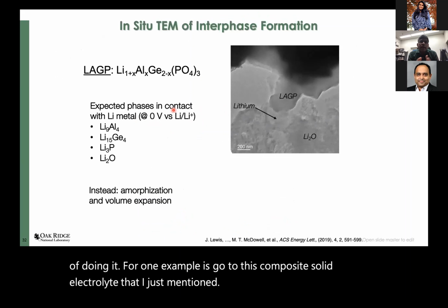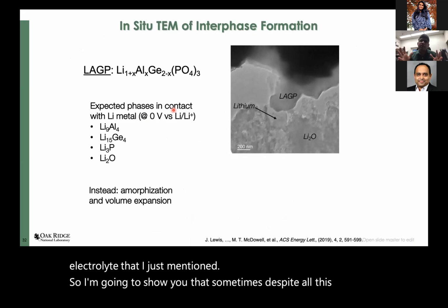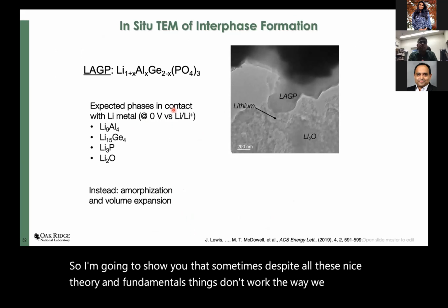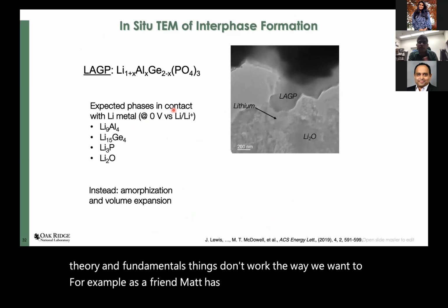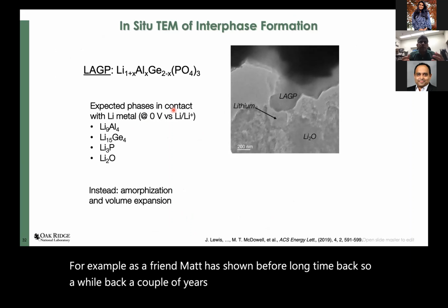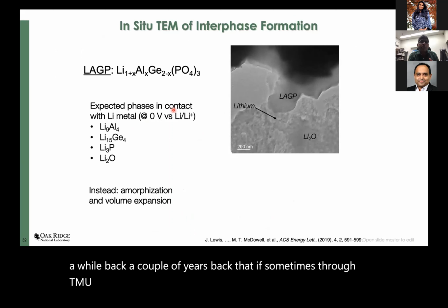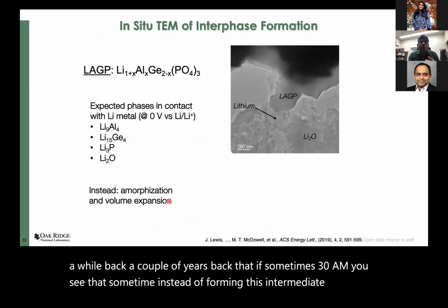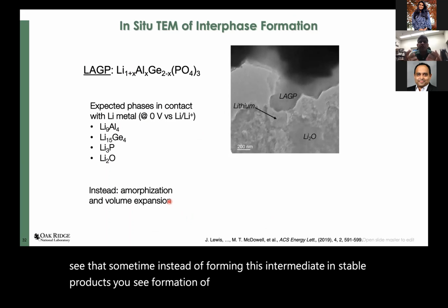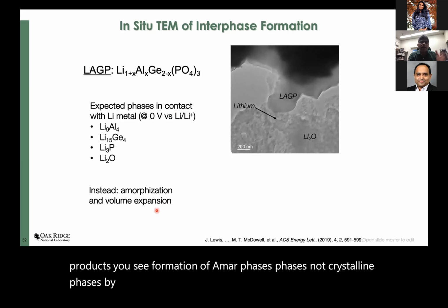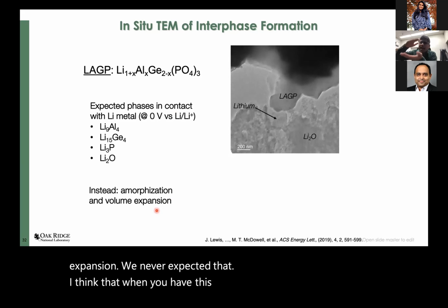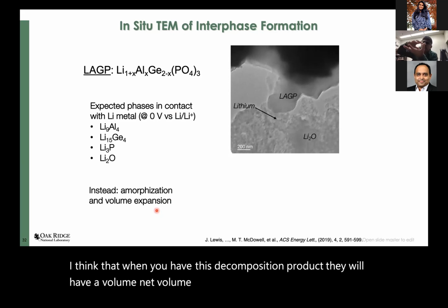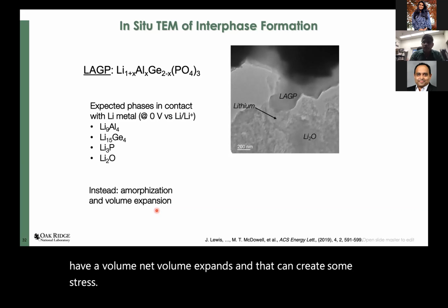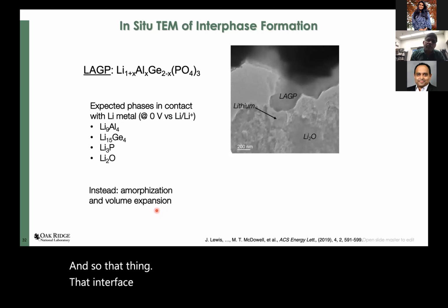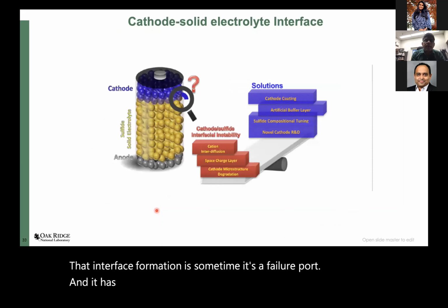So I'm going to show you that sometimes, despite all this nice theory and fundamentals, things don't work the way we want them to. For example, as my friend Matt showed a couple of years back, in in situ TEM you see that sometimes, instead of forming these intermediate unstable products, you see formation of amorphous phases, not crystalline phases, and there is volume expansion. We never expected that when you have this decomposition product, it will have a net volume expansion, and that can create some stress. So that interface formation is sometimes a failure mode, and it has been clearly shown.